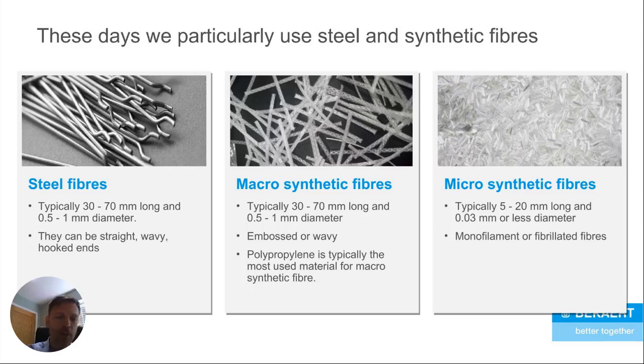Important that we look at different types of fibers on the market. So I've talked to you about steel fibers today. Fibers that have been around for a couple of decades as well. On the right hand side, you can see microsynthetic fibers, and these are extremely small, tiny diameter, millions of them per kilo, therefore tens of millions of them per cubic meter. They can be added to concrete and aid against early age plastic shrinkage cracking, and sometimes they can replace air entrainment agents. So they have a couple of advantages that you cannot get with traditional steel or steel fibers.